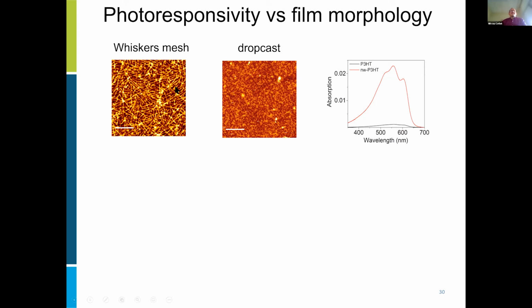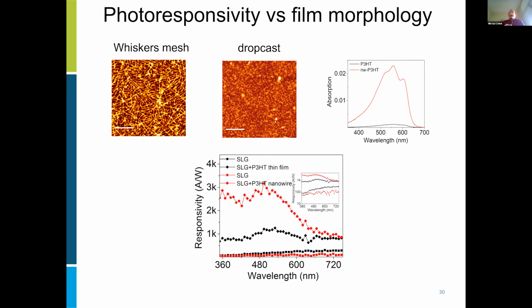So that will create a lot of scattering and rescattering and reabsorption of light, both into the conductive polymer and into graphene, basically. And that is supposed to increase the sensitivity or responsivity of the material itself. If we look here at the absorptivity of the nanowire mesh polymer versus the thin film polymer, we see that it's dramatically increased compared to the thin polymer film. And here we compare polymer films of the same thickness. Making devices out of this